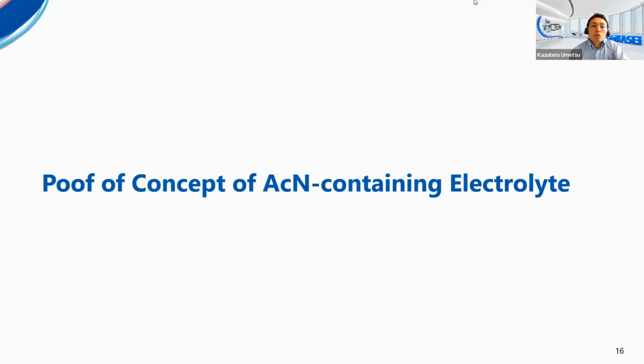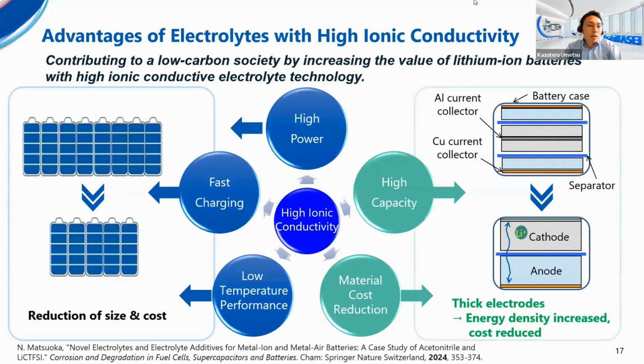Finally, I'd like to introduce the proof of concept results of acetonitrile-containing electrolyte. Taking advantage of its high ionic conductivity, acetonitrile contributes to improving C-rate performance, fast charging, and the low temperature performance of lithium-ion batteries. These improvements will make it possible, for example, to reduce the size and cost of battery packs. In addition, acetonitrile makes it possible to realize thicker electrodes without giving up the C-rate performance, which contributes to increasing the energy density and reducing material cost. So in this way, acetonitrile technology contributes to a low carbon society by increasing the value of lithium-ion batteries with its high ionic conductivity.